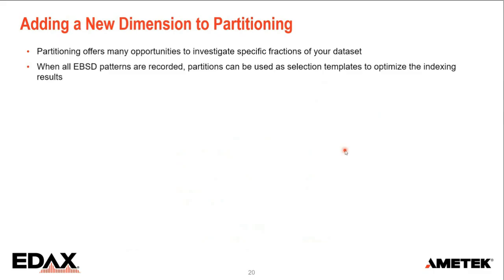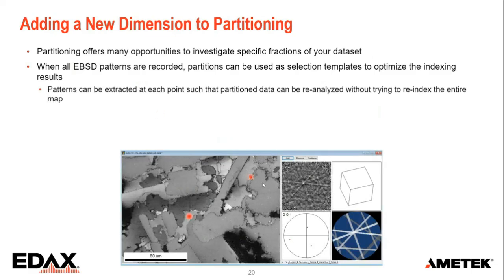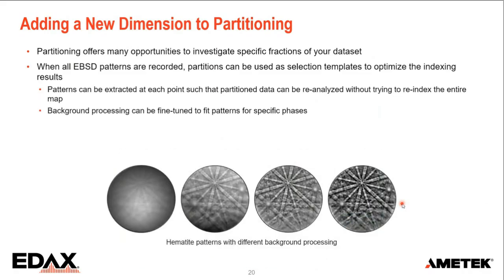And we can even use that when we store all the EBSD patterns as well. So we can then just select certain parts of the data set to optimize indexing. So for example, we can extract diffraction patterns at every point. This is this flexi view I was talking about before. We have a pole figure, a pattern, a reconstructed pattern, orientation representation in a wireframe. You can just move your mouse over the data set, and this is just dynamic. Wherever your mouse is pointing, you can see the result. And when you click somewhere, you can extract that pattern, modify background processing, modify the phase, etc. So you can really maximize the indexing performance.